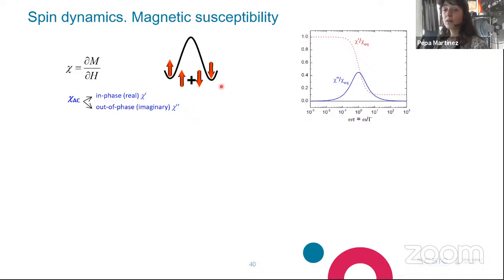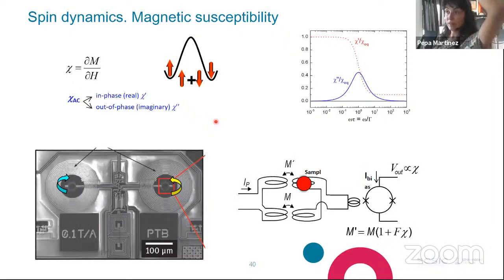For instance, in the case of particles blocking their magnetic susceptibility, one expects the presence of a peak in the imaginary part and a dip in the real part. This is so because at low frequencies the particle is able to follow the externally applied magnetic field, that means flipping its magnetic moment at the rate of the external field, but at larger frequencies it is blocked, it is not able to do so. This process can be done classically over the energy barrier created by the anisotropy, but also through quantum tunneling of the magnetization.